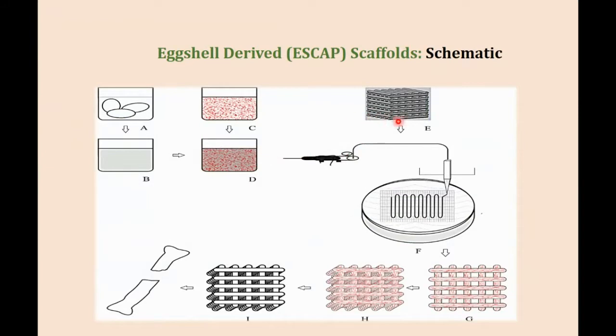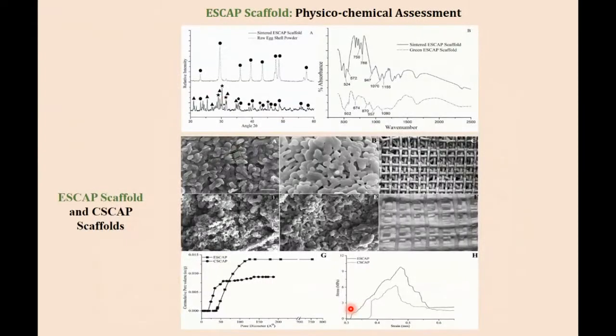So as you see here, we made the 3D printed structure and then directly we got the scaffold. And this scaffold was compared with the chemically derived hydroxyapatite scaffold, and we got much more remarkable results with eggshell based samples as compared to the chemically derived one. In fact, with both seashell and eggshell, we got better results than the chemically derived one. Perhaps it is because the chemically derived one has a perfect hydroxyapatite structure. However, in the case of seashell and eggshell based materials, there are stoichiometric defects that may show better resorbability of hydroxyapatite, which is actually degrading much faster in vivo, giving us a higher concentration of calcium and phosphate at the site. Therefore, it is promoting us to deposit the bone-like structure on the site much better.